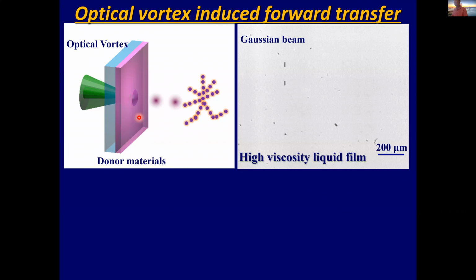Is this true or not? At first, we pump the donor film with a Gaussian beam. At this moment, the donor material has very high viscosity, over 4 Pascal seconds. This viscosity corresponds to a honey drop or mayonnaise. Generally speaking, such a material is not available for inkjet printing technology. We pump this film with the Gaussian beam.